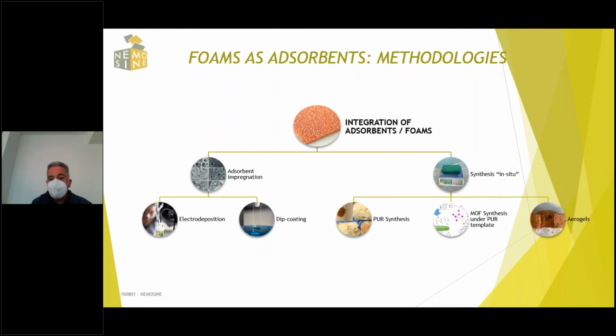In the first process, the impregnation of the sorbent materials inside of the foams, we can use electrodeposition processes or dip coating processes. On the other side, for the in situ synthesis, we can work with the typical polyurethane synthesis. We do both the synthesis of the MOF and the synthesis of the foam at the same time, and this will be a MOF synthesis under a polyurethane template. And finally, a new kind of foam that can take advantage of these requirements is the development of aerogels.